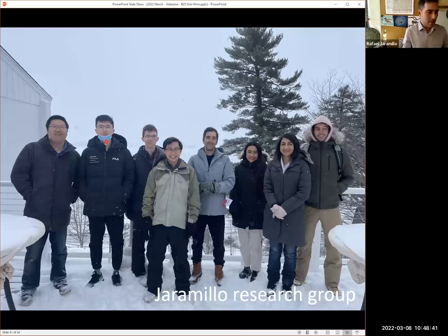Other than that, we don't have a big scrubber. If you saw our setup, you'd say, really? That's it? One of the benefits is that because it's MBE, we don't use more than about 2 sccm. It was determined that the 2 sccm running through the pumps and then going up the stack, where that particular exhaust manifold gets 400 CFM, gets diluted well below the limits. So we can just send it right up the stack. I have all sorts of stories about that, as you can imagine.